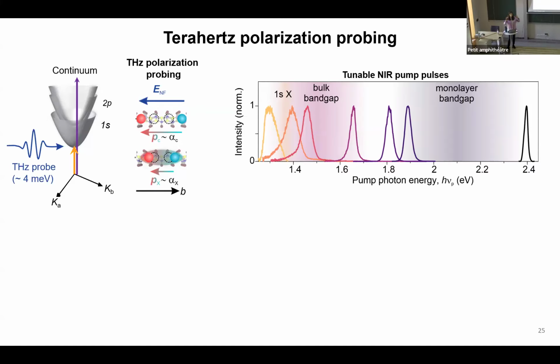How does it happen? Take an electron hole pair that is free, so they are not bound into excitons. It means the hole and electron interact less with each other. So when you shine an electric field on this free electron hole pair, they will be more polarizable. They can go farther from each other, right? However, when you have a bound quasi-particle, which is an exciton, for instance, when you shine terahertz radiation on this exciton, you see that there is less polarizability because the electron and hole are Coulomb bound together. So already with this terahertz spectroscopy, we can gain information about the nature of the binding state of the electron and hole pairs that we are studying.